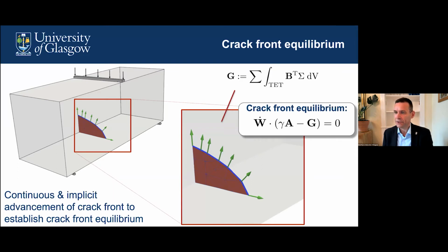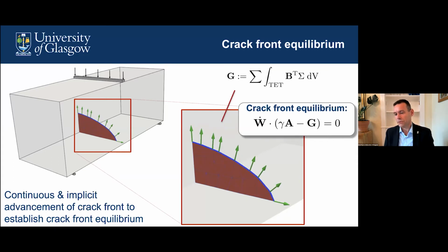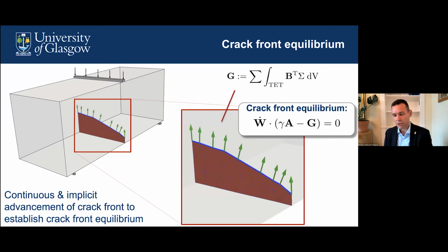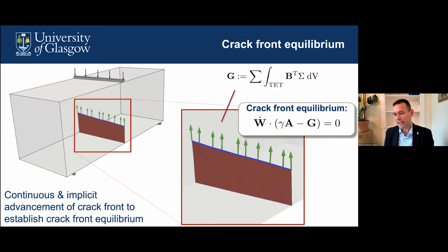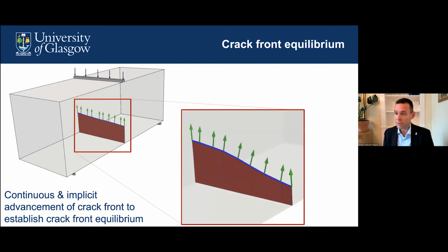It's important to say here that we are solving simultaneously for the equation of linear momentum balance and the crack front equilibrium equation at the same time. So there is no post-processing going on here. The green arrows, these configurational forces, are a natural consequence of our analysis. So what we end up with is a continuous and implicit advancement of the crack front, continuously re-establishing crack front equilibrium as well as elastic equilibrium. So you can see here that the crack propagates, it negotiates the free boundary and carries on propagating. When you animate it, you get a very smooth, continuous advancement of the crack front.